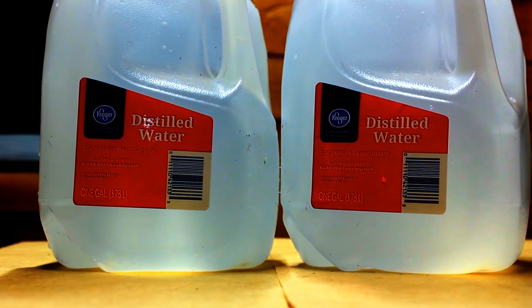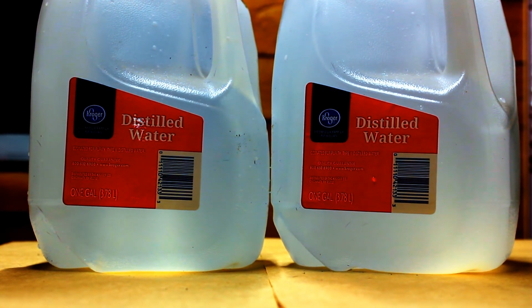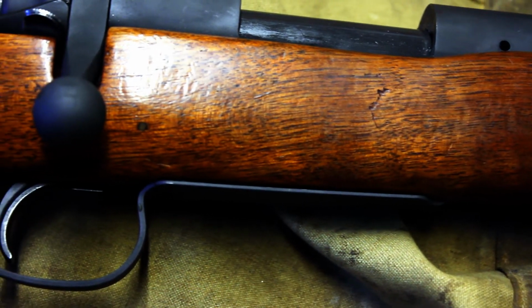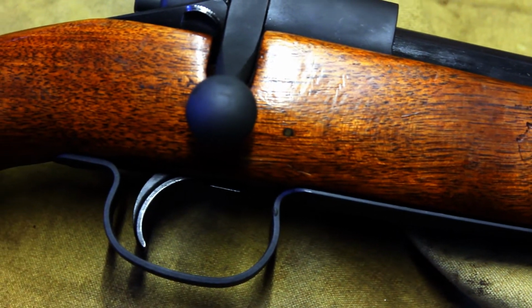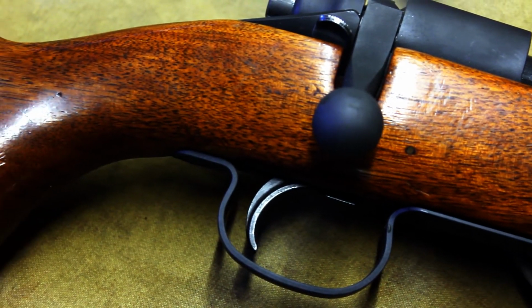Now it's important to note that clean distilled water should be used so as to not contaminate the Parkerizing solution, which could negatively affect the finish on the firearm. The next step is seasoning the solution. This step only needs to be done once before the first job. Seasoning ensures the first firearm to go in the finish gets a healthy coating of Parkerizing. Without seasoning, the solution is weak and deposits a weak coating.